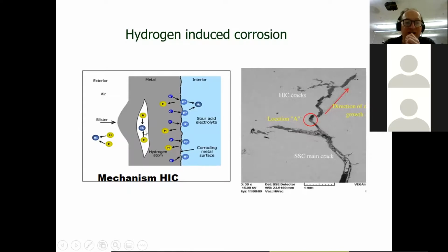And at some point it can make hydrogen gas, H2 you see there, the little blue bubble. And hydrogen gas, of course, will expand because it's a gas, and it will create a void inside the metal. It will make it blow out, it will form a blister. And eventually that will burst, the hydrogen will come out and it will form water, or react with air to form water. So the mechanism for hydrogen-induced corrosion essentially requires a liquid which contains hydrogen, an acid or electrolyte which is low pH. We have some corrosion on the surface. We form hydrogen atoms which diffuse into the metal. There's these yellow bubbles. And at some point inside the metal, the hydrogen atoms join together to form a hydrogen molecule, which expands inside the body of the metal, causing it to bulge and form a blister. And of course, it will form cracks and lead to stress corrosion cracking. So that is the mechanism for hydrogen-induced corrosion.